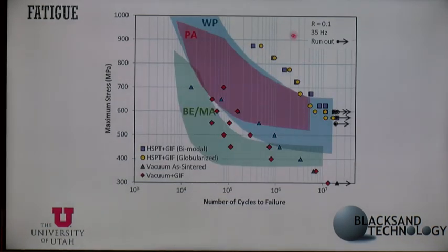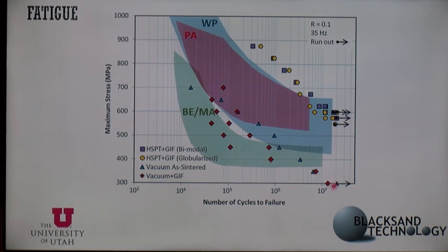And as you can see here, this is fatigue. So this is how many cycles it goes to. This line right here, that is 10 to the 7th, is basically our cutoff. There's a generalization that if a material can undergo 10 million cycles, or 10 to the 7th cycles, it's considered to go on infinite. It can undergo that stress for an infinite amount of time. So anything past this line is generally extremely good, and it's going to last you a lifetime of service, whatever your parts may be.